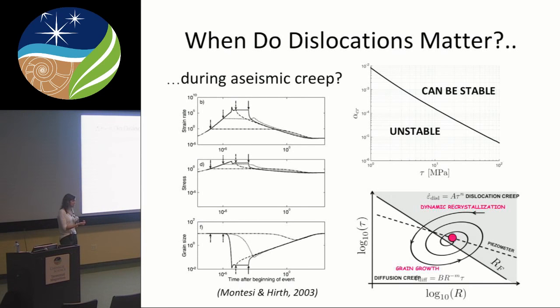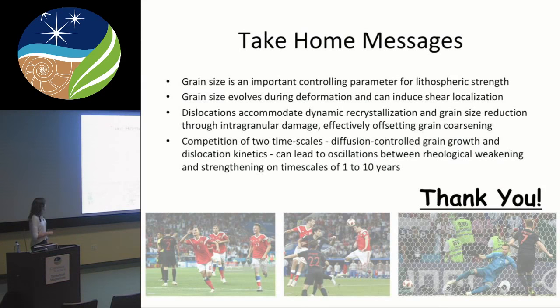And then during the stage of the aseismic or post-seismic creep, you're seeing how your material is strengthening back or sort of healing or recovering from that initial pulse. And what the previous study shown before is that you grind your grains down and then they slowly by diffusion start to grow back up. What this kind of oscillatory behavior would imply is that instead of just smooth coarsening, you'll be kind of oscillating or potentially kind of having a characteristic periodic strengthening and softening as you're reaching your steady state. And that, I think, is the last part of my talk.